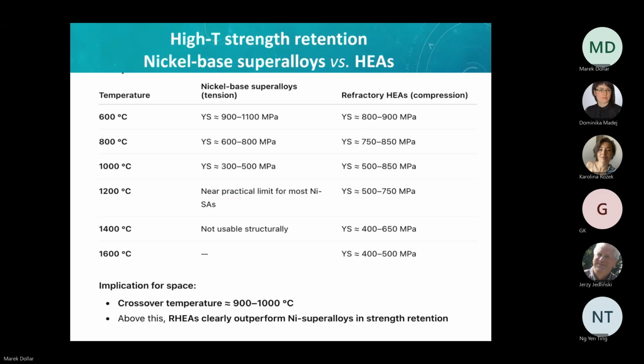Let's compare properties that we have available now, measured in laboratories of nickel-based superalloys, mostly properties measured in tension. Because of manufacturability, most data you are able to find in literature are for compression, but more and more they are complemented by comparable properties in tension, so tensile properties. Look at 600 degrees C, you see pretty much the same, no big difference. Likewise, 800 degrees C, these are the ranges.